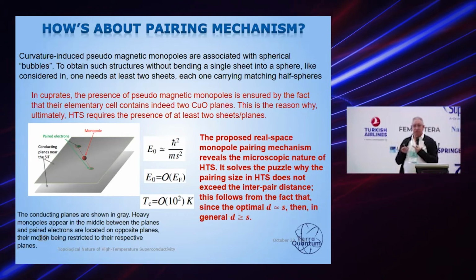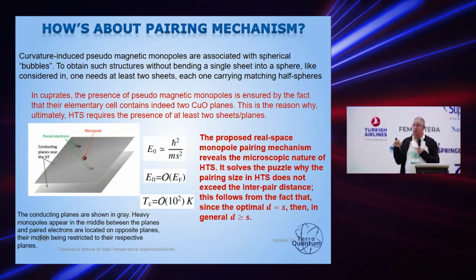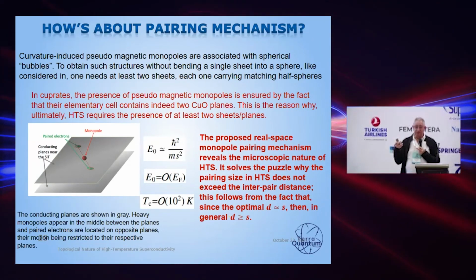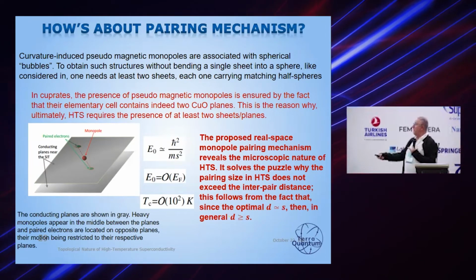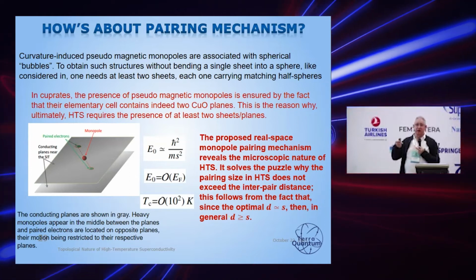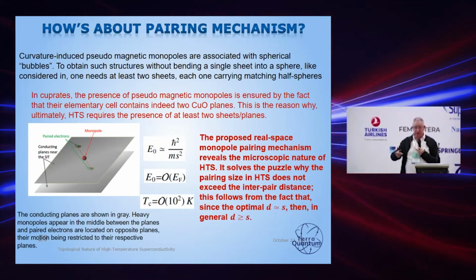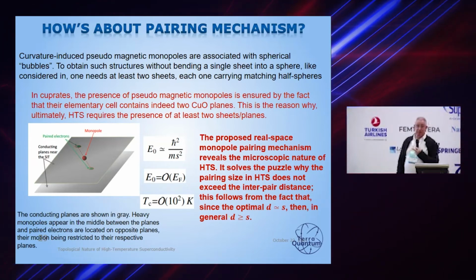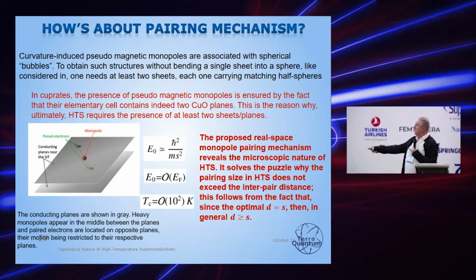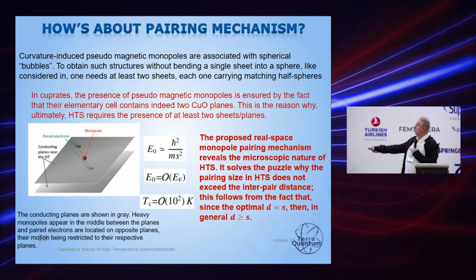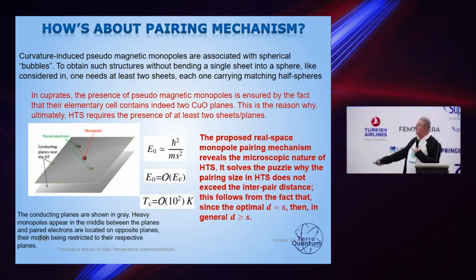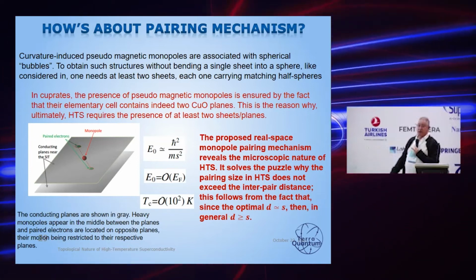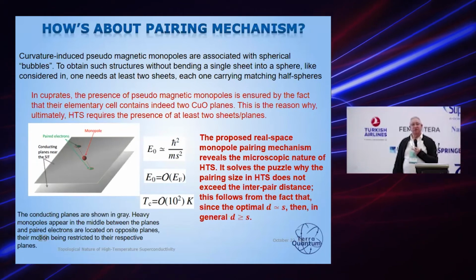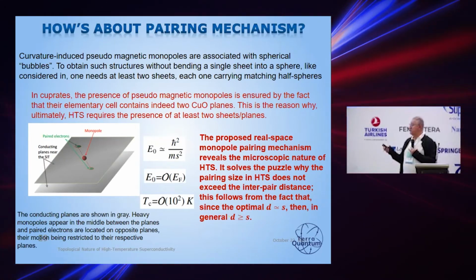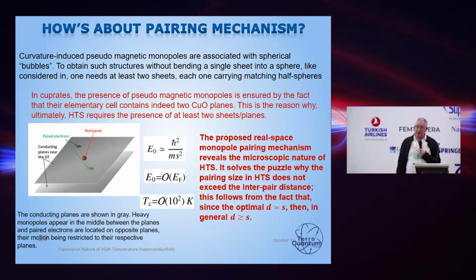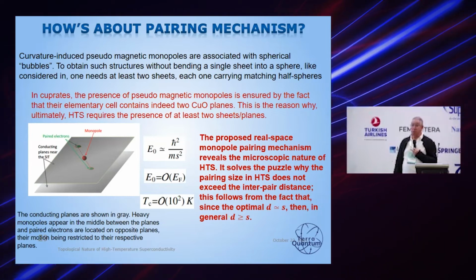This is a simple quantum mechanical problem because this pseudomonopole and its pseudomagnetic field is going to bind electrons located in these planes, and we can estimate the binding energy. This is the distance between these planes, which is of the order of the electron wavelengths, and then we immediately see that this energy is, up to the numerical coefficient, of the order of, or maybe 10 times less than, the Fermi energy of the electrons, meaning huge.